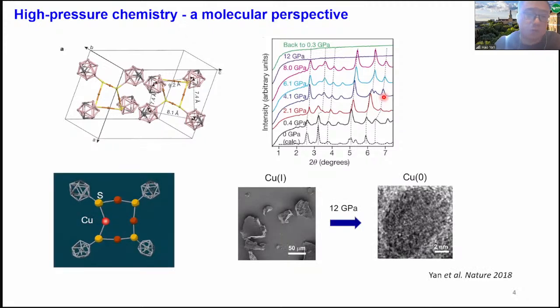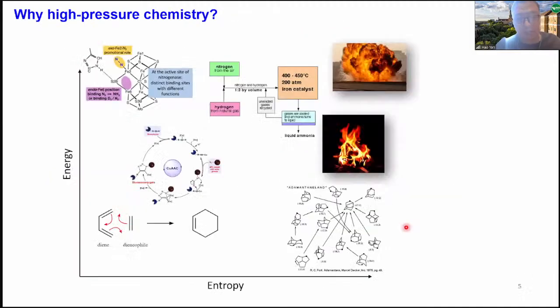What's actually interesting about this system goes into the molecule. In this particular one, we're seeing that the bond angle around this otherwise linear copper actually starts to bend under pressure, and this drives a charge transfer that eventually leads to a reduction of copper 1 to copper 0, solely driven by mechanical force. So this, I think, is a wonderful example that shows that when we consider the high pressure chemistry of molecular compounds, the details really lie not in the long range order or the lattice, but rather in the local structures within the molecules.